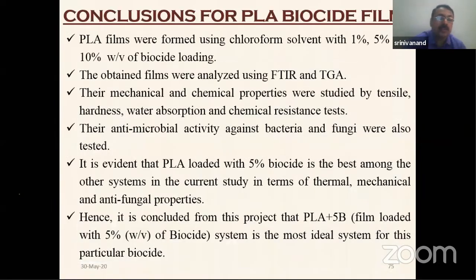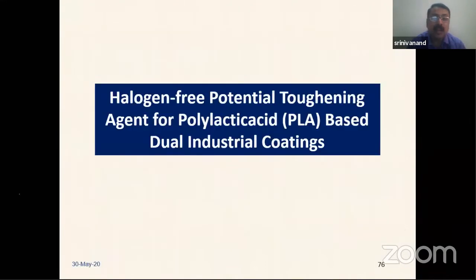So this is the conclusion. PLA films, we made them using biocide, and we observed the interaction with FTIR and TGA, and we measured the hardness. And finally, we concluded from the study that PLA with 5% biocide is the most ideal system for packaging applications. And similarly, the present work we are carrying out in our lab is because, as I told you, most of the industrial applications use halogenated solvents, which are very toxic to the environment.